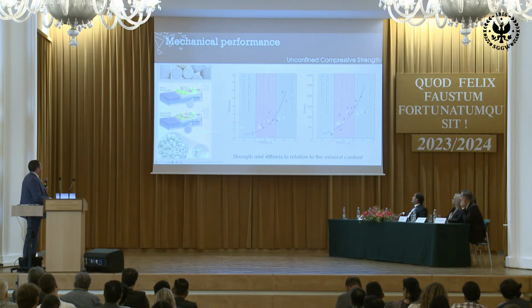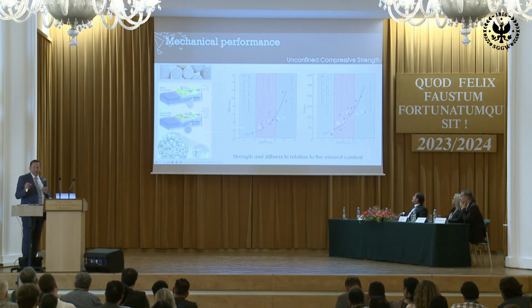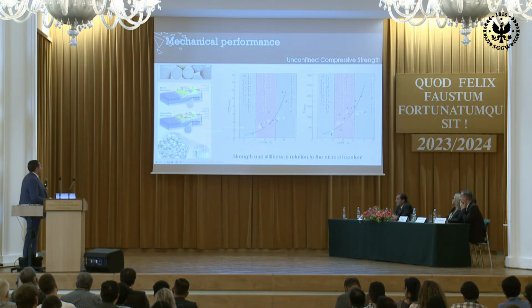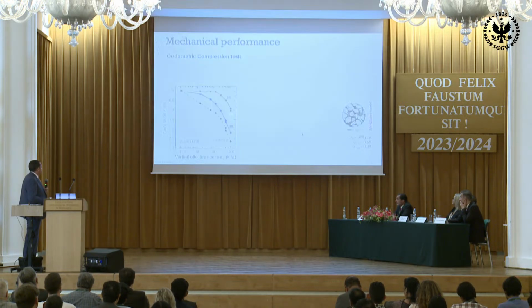So for instance, if you are dealing with liquefaction and erosion protection problems, a small amount of calcite is sufficient to create the needed cohesion in the material. If you have to increase the bearing capacity, you can increase the domain a little bit and go for higher strength, as I was mentioning, almost 12 megapascal. So briefly, those are conventional geotechnical things.